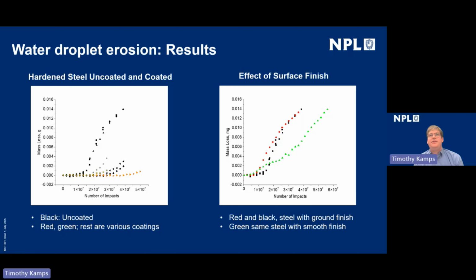So on the left-hand side of this slide here, we can see hardened steel in the uncoated and coated condition with various coatings being tested. It's clear to see that the system is able to differentiate between the different coatings. The black is the uncoated and the other colors are various coatings. But more than this, what we can see is that if we needed to make a decision based on the lifetime and the cost of maintenance, we can optimize the lifetime of the part based on these factors.